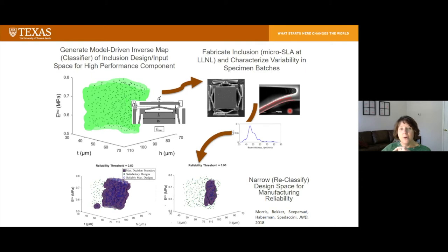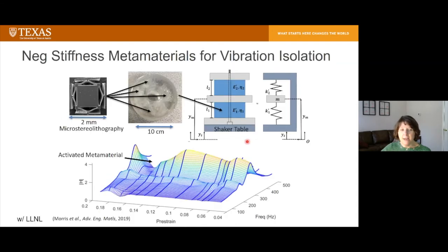We can test them for modulus. We can also characterize their geometric resolution and accuracy. And then from that, we get distributions of geometric accuracy and material properties. We can use our original classifier combined with the Monte Carlo sampling of those distributions to narrow our design region of interest, to only the design points that are not only high performance as predicted by our simulations, but are also likely to be high performance even given the variability that we observe in geometry and material properties. And so that's how we got these excellent material properties the first time around.